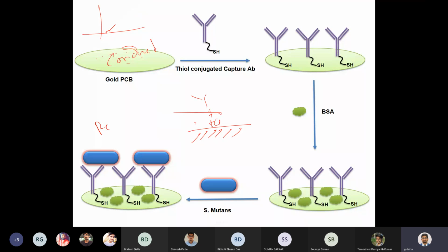Sometimes we are using graphene oxide or reduced graphene oxide, so that at least we have very good conductivity on this surface. Otherwise, if you just use gold, then you use EDC NHS, carboxylic acid formation, then EDC NHS, then antibody. There are so many steps. They actually heavily hinder the electron transfer rate. So basically, your signal will be decreased.